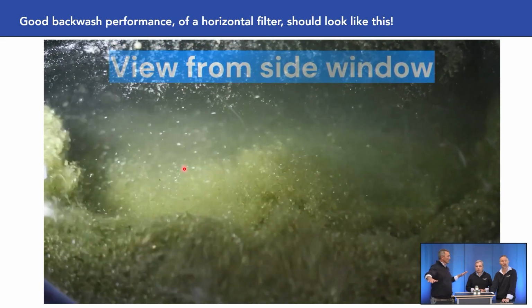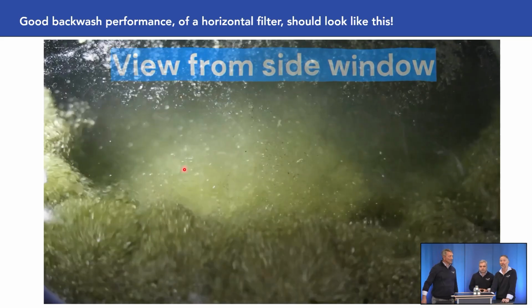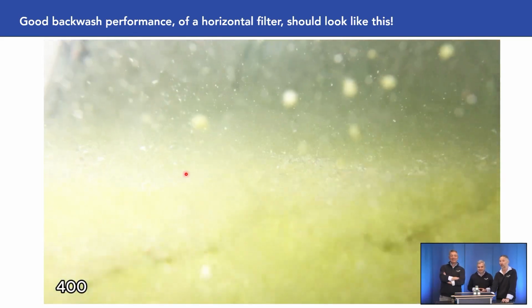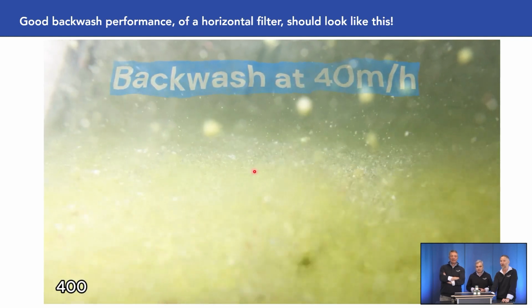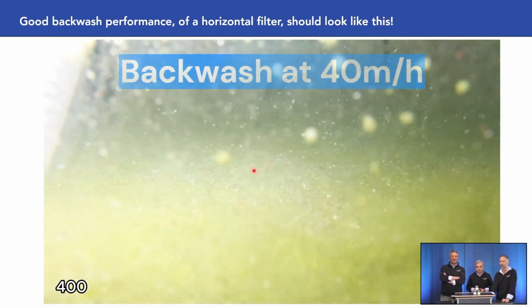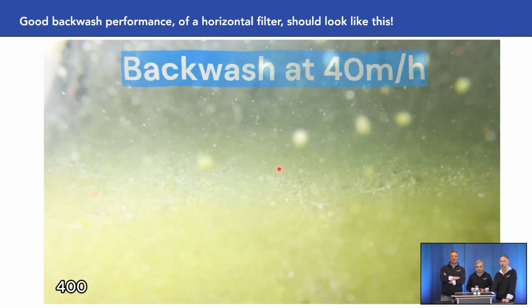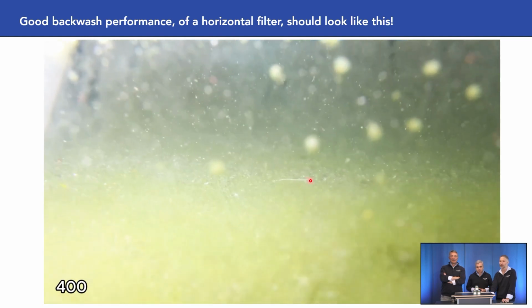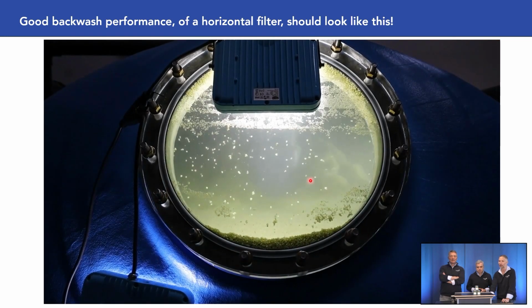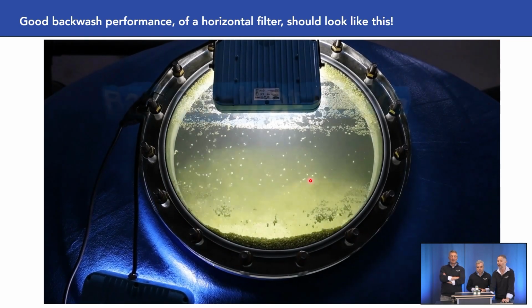Equally through all over the surface? Throughout the whole surface, yeah, to the edge. And this view was actually from the side video, from the side window. So it showed that the overall bed expansion throughout the whole filter was great. Then at 40 meters per hour, you can see even better bed expansion and fluidization. We then bumped it up to 45 meters per hour.